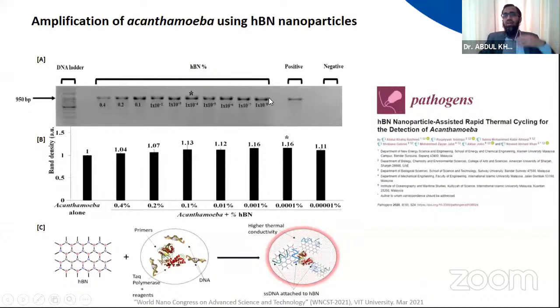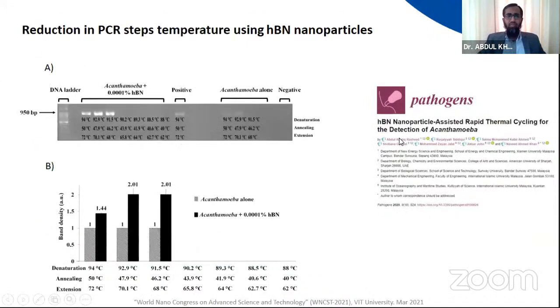The reason being, TiO2 and graphene are relatively expensive materials compared to hexagonal boron nitride. Even though nowadays graphene is being produced at a much cheaper price, 2 years back it was still regarded as an expensive material. So we took up HBN, we synthesized it, and we determined that HBN can also give you enhancement, but the fold of enhancement may not be as good as graphene or other high conducting materials. And we again came up with a mechanism which is explained in this paper. You can refer to this later on.